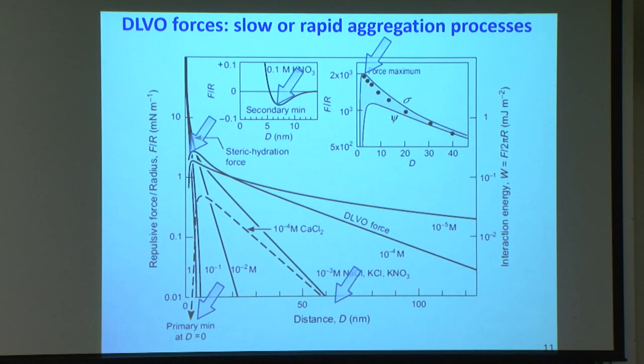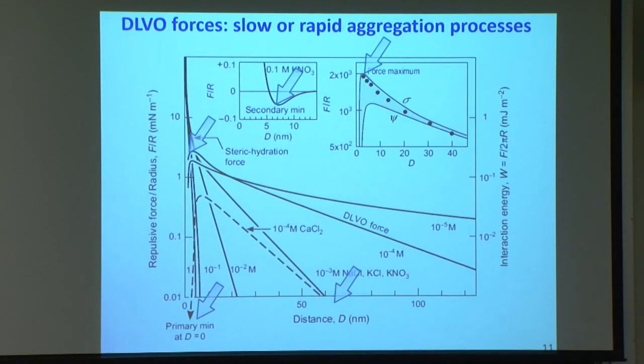Okay, so what is the DLVO interaction? If one plots the force, this would be the repulsive force divided by the radius, because forces usually are scaled by the radius, as a function of distance. This shows the most common interaction in water between charged surfaces, positive or negative, where you get an electrostatic repulsion, which decays exponentially with a decay length that depends on the Debye length, meaning it's longer ranged the more dilute the solution. And at small distances, the van der Waals forces come in.